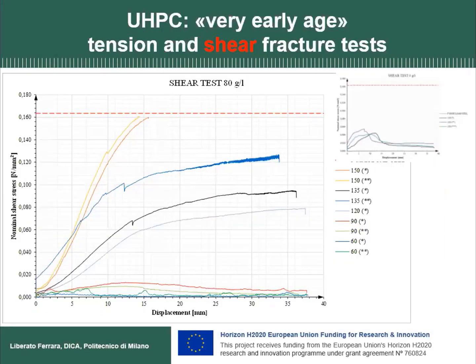And also here you can detect, this is an example of the mix with 80 kilograms of fibers per cubic meter, or as is written here, 80 grams per liter. And you can see it evolving from 1 hour up to, in this case, 2 hours and a half. You go from a fluid to solid transition, and at a certain point we reach the maximum capacity of our load cell. On the top right, you have the same tests for the matrix, which remained, by the way, well below the load capacity of the cell.